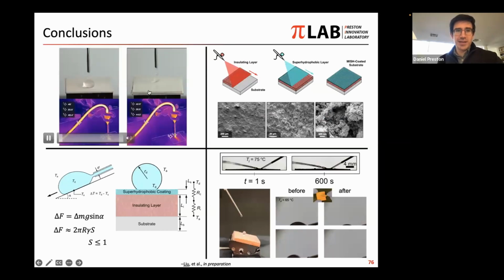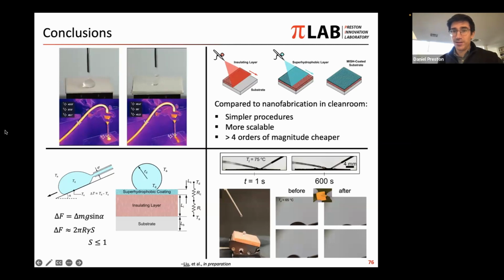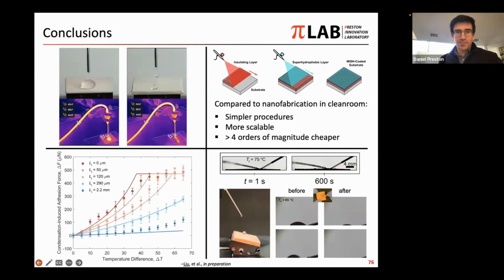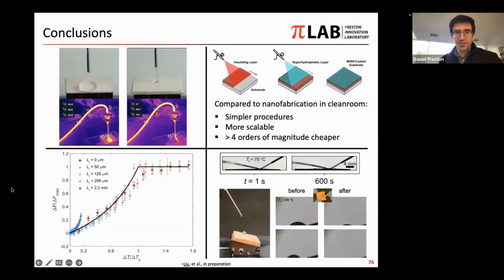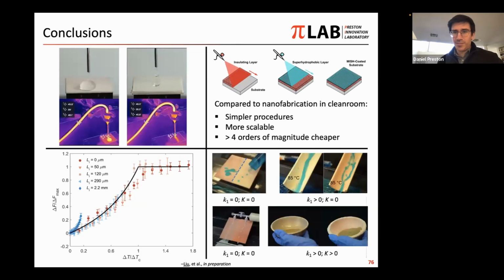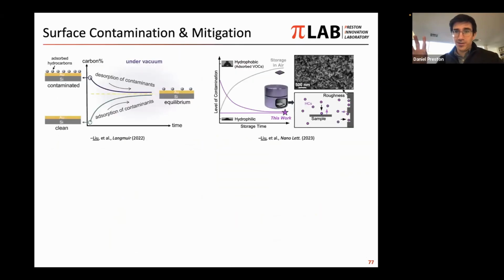So we can conclude by saying we developed this coating using the thermally insulating layer that repels hot water droplets. It's scalable. We predict that it's about 4 orders of magnitude cheaper than fabricating a surface in the clean room. We looked at modeling the performance, comparing it to experiments, and also non-dimensionalizing it. We were encouraged by that result. Then we also did a bunch of demonstrations to show how we might use this kind of spray-on mesh coating in our ongoing work. Just touching on the two things earlier, we looked at contamination in ultra-high vacuum, and we also looked at mitigating it using ultra-high surface area clean storage containers.